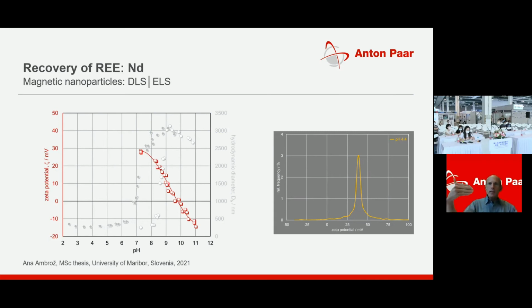With the diminishingly small zeta potential, the electrostatic repulsion between nanoparticles becomes weaker and particle agglomeration takes place. This is evident by the increase in the hydrodynamic diameter with increasing pH.